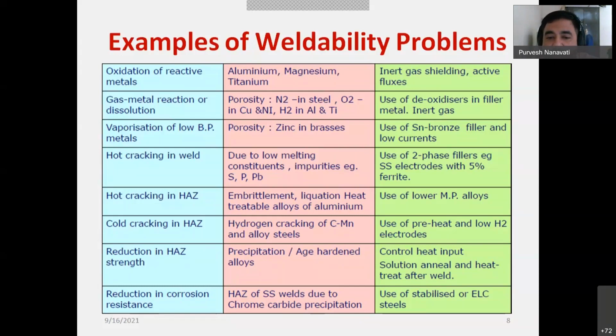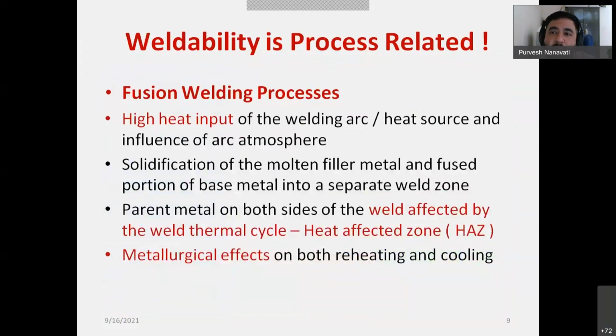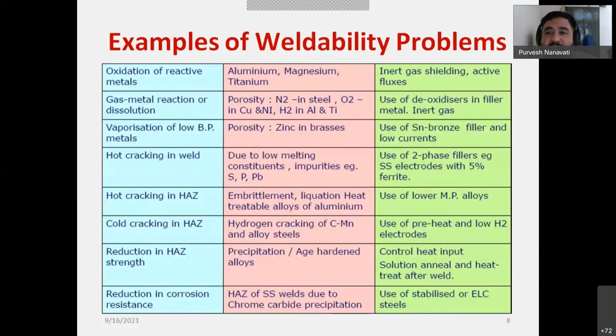So we have to control the heat input so that we can control the cooling rate, and solution or annealing heat treatment after welding is recommended for those steels. And reduction in corrosion resistance is due to chromium carbide precipitation, as I mentioned. So we have to use stabilized or ELC, extra low carbon grade steels.